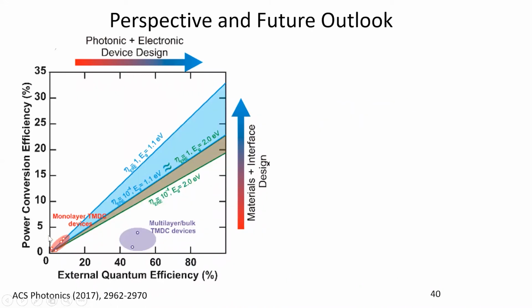and where the community is, the monolayer devices are still pretty bad. They are in the sub 5% regime. Even their external quantum efficiency is not very good, just because they are not absorbing as much light and not much light design has gone into it. Multi-layers can absorb a lot more light, so they can have a higher external quantum efficiency. But then again, open circuit voltage engineering has not been done for them, and therefore they are sitting over here.